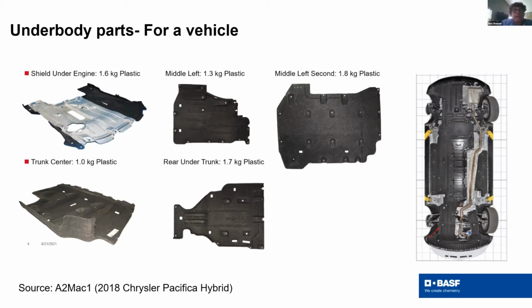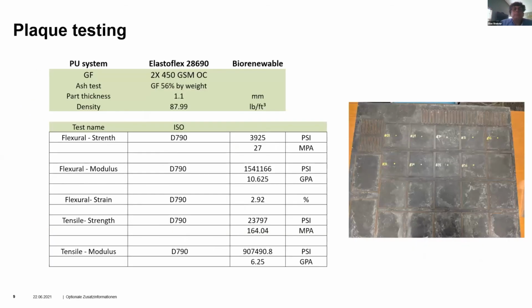So we thought, like, if we want to go after this market, we have to provide a higher strength. Not only that, it will be a lighter weight. So for this work with our customer CIE, we started with a coupon size, and then we will expand that to a prototype part. So we started with utilizing a polyurethane system that has a biorenewable. It has the highest biorenewable in the market. And we tried to go to the thinnest possible part we can make, which is 1 millimeter. And we did all the mechanical performance for that.